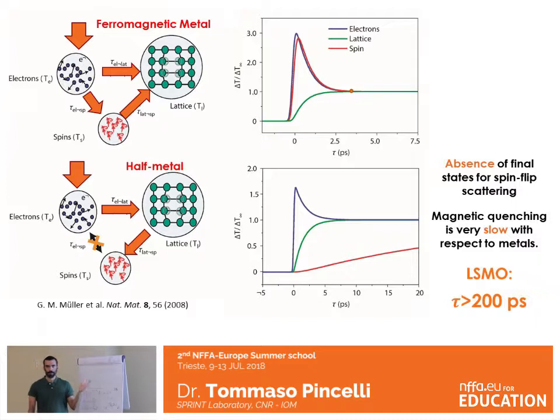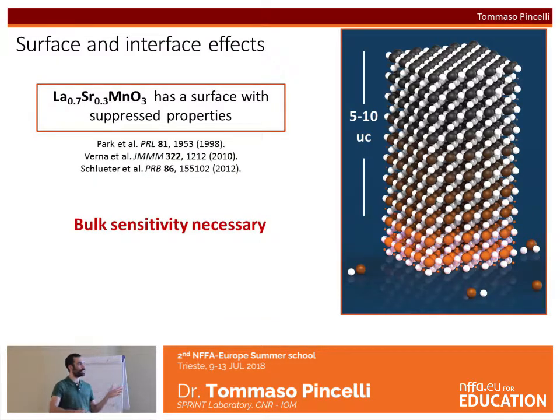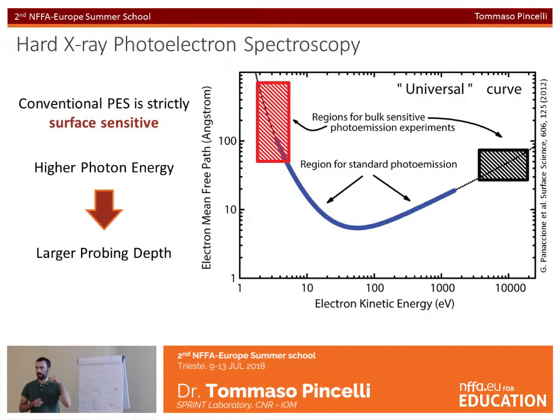Now there is a big problem with performing photoelectron spectroscopy with oxides. They tend to have significantly different properties at the surface. So you need to look into the bulk. And to do that with photoelectron spectroscopy, you need to increase the photon energy, and thus the energy of the photoemitted electrons, and let them exit from a larger portion of your solid without losing the energy information.